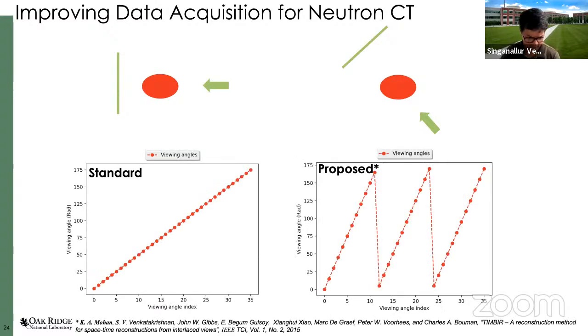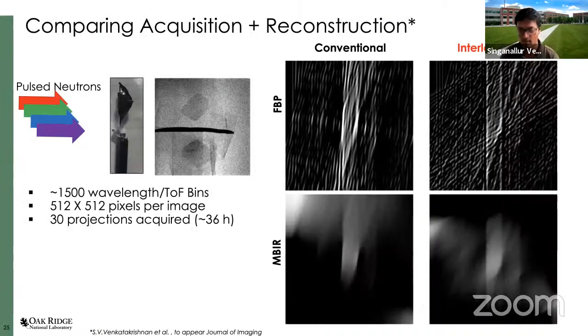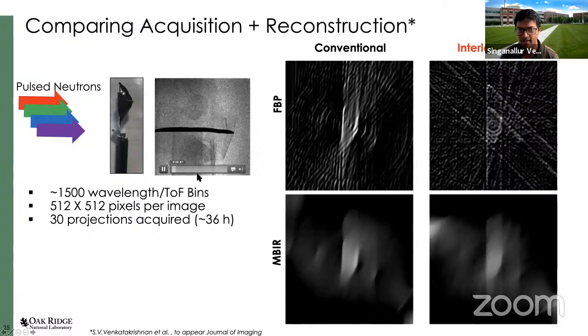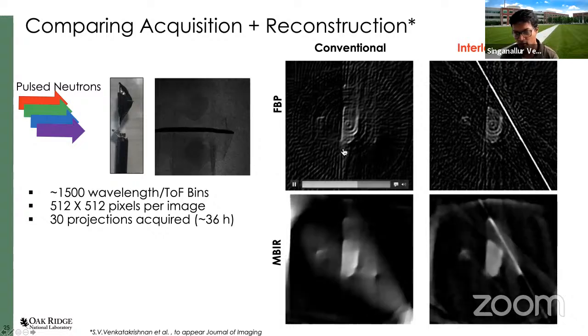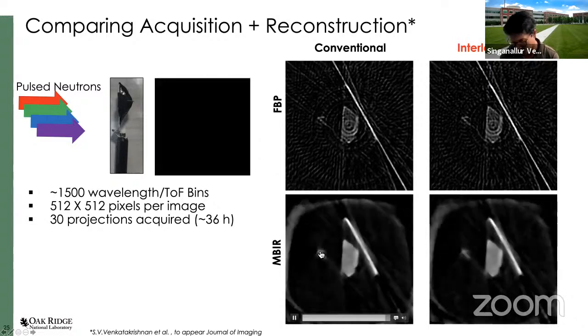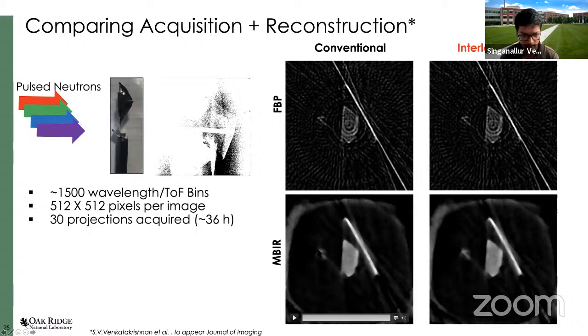And this idea is based on a previous colleague's work for time-resolved CT, but now we have brought this type to the hyperspectral case. And this can be very useful. For example, we did an experiment where we have two magnetite crystals and we collect this extremely noisy data. And what you're looking at is real-time reconstructions. Of course, these are very slow processes because it takes 36 hours to do a scan.